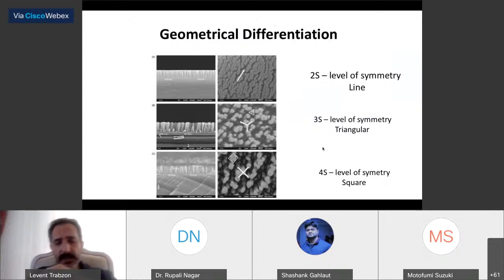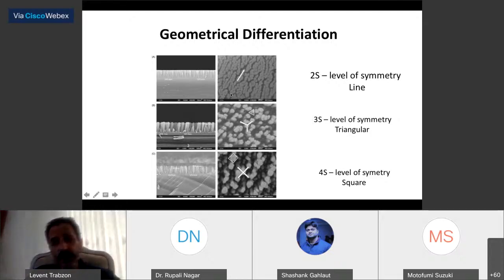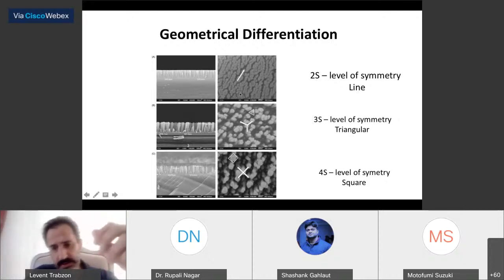So as an experimental setup, we have grown different silicon columnar structures having different levels of symmetry. On the top, we get one elongated in a certain direction. We call that 2S level of symmetry, a line kind of symmetry. If you arrange changing the turning speed of the substrate accordingly in three different sections, you get a triangular level of symmetry. We call that 3S. Or if you get the square-like cross-sectional columnar structure, as you see over here, we call that 4S structure.